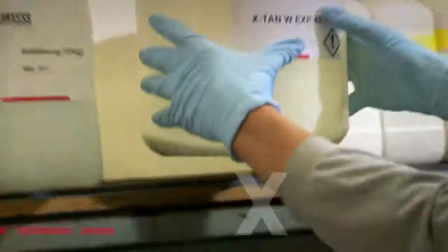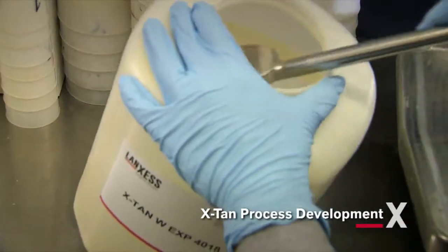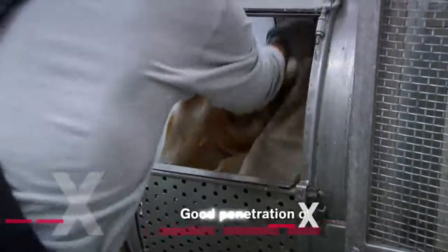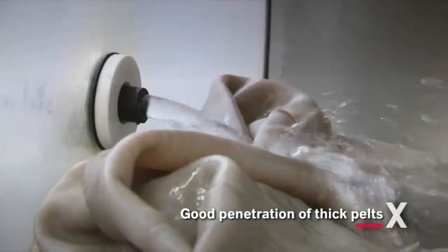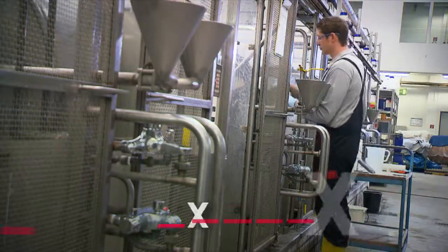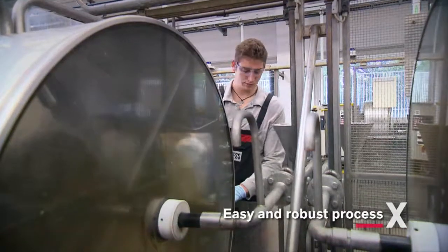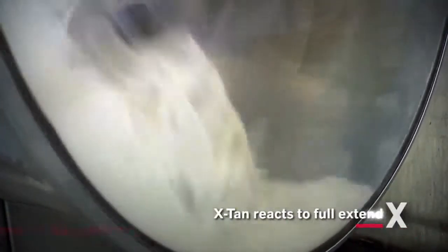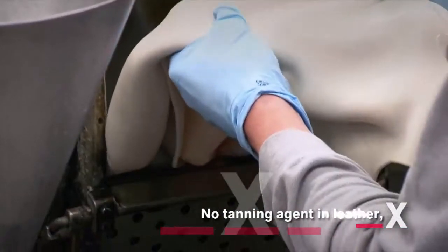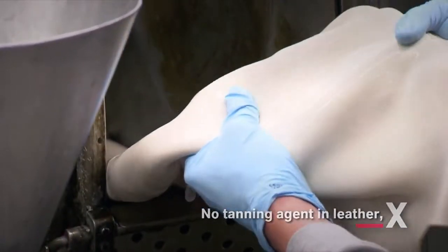The Leather Technology Center in Leverkusen developed an easy and very robust tanning process for X-Tan. During the process, no conditioning with acid and salt is necessary in order to achieve a good penetration into the pelt — in other words, the X-Tan process does not need a pickle step. The process has been optimized in terms of X-Tan quantities and pH profile to ensure a full conversion of the pelt into leather and at the same time a complete consumption of X-Tan. If an excess were added, it would be neutralized into polyurea compounds, so no free reactive tanning can be found in the leather, the shavings or the effluent.